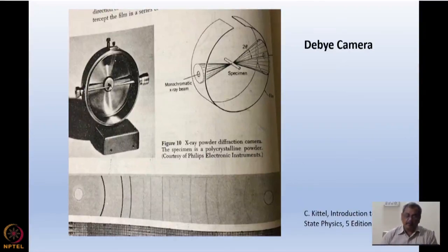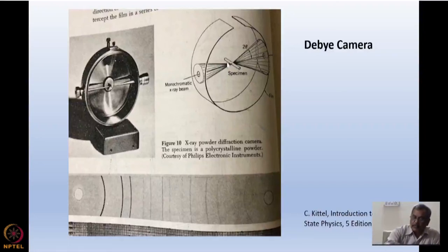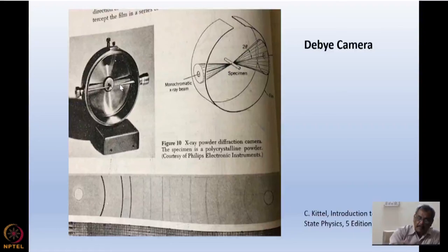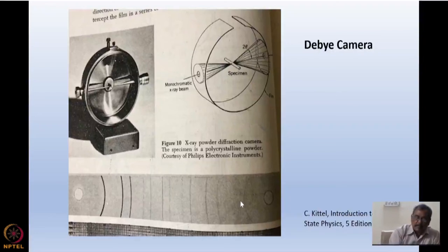This is the very beginning of our knowledge about X-ray diffraction. Basically this is a monochromatic X-ray beam, this is a specimen, and the rings break up into low angle and high angle. The back-scattered beam is high angle and the forward-reflected beam is low angle. The back-scattered X-rays, because of the atomic form factor, are of much lesser intensity than the forward scattered beam because for almost all atoms in case of X-rays, the form factor falls off with increasing θ or Q.